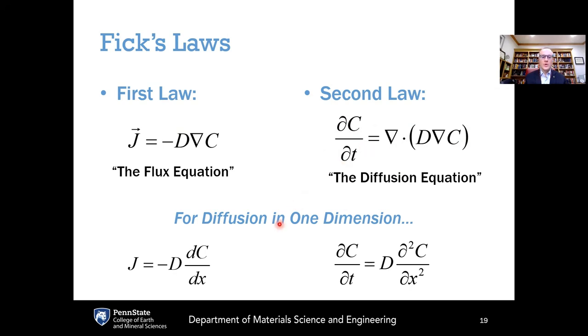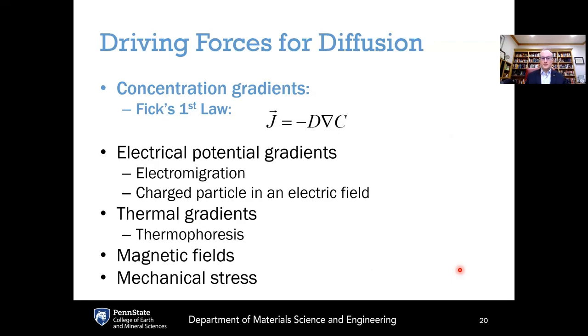If we have diffusion in one dimension, the flux equation here is just flux equals minus the diffusion coefficient times the concentration profile along that one direction. And in one dimension, Fick's second law, the diffusion equation, is just the partial of concentration with respect to time is equal to the diffusion coefficient D times the second partial derivative of the concentration with respect to the spatial coordinate x. So Fick's first law is assuming that the only driving force for diffusion of matter is the concentration profile of that same species.